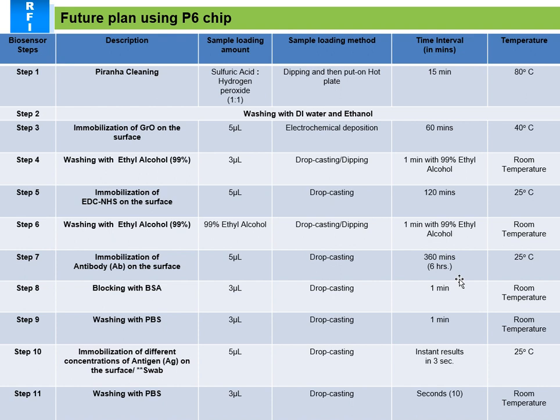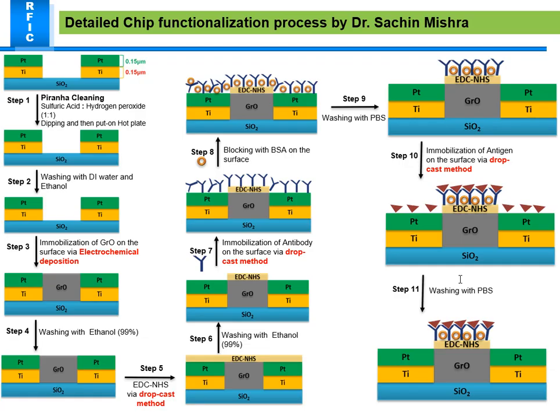And then we immobilize the antibody onto the surface using 5 microliters or 6 microliters, depending on the surface area we have, and then I use BSA and wash with the PBS, and then the antigen, and then wash with the PBS. In this series, in all these steps we have to measure the capacitance value, so that we can compare whether our capacitance value is increasing or not. It depends on the concentration of the antigen also. So it goes on, and this is the schematic representation of all steps.